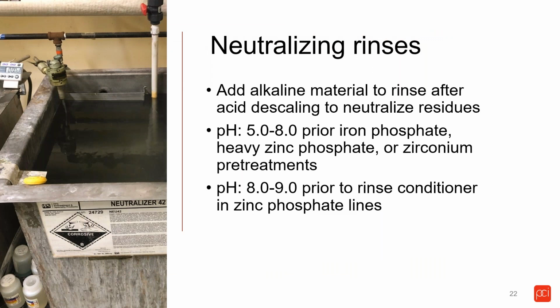So after your acid descaler, we highly recommend using a neutralizing rinse over a regular city water rinse with a high overflow, because a neutralizing rinse is an alkaline material that does a much better job at neutralizing acid residues. We typically recommend a city water rinse after the neutralizing rinse, but if you don't have the space for that and you're going directly into pretreatment, maintain the pH between 5 and 8 for an iron phosphate, a heavy zinc phosphate, or zirconium, and a pH of 8 to 9 for the rinse conditioner on a zinc phosphate line.